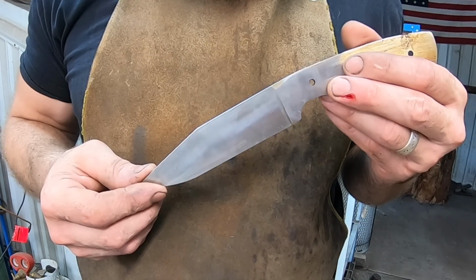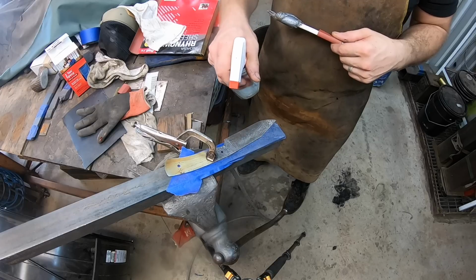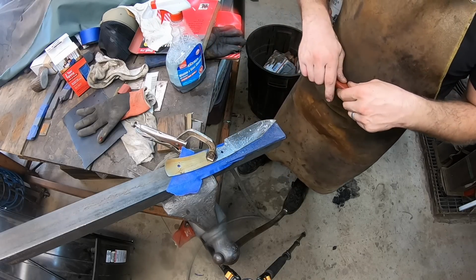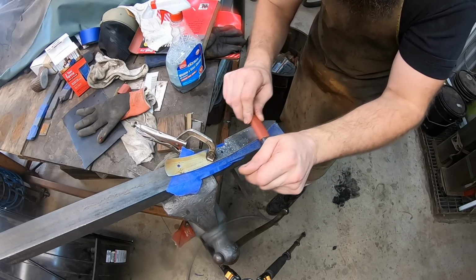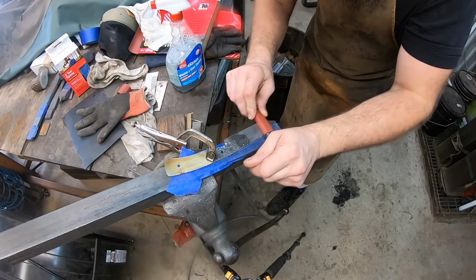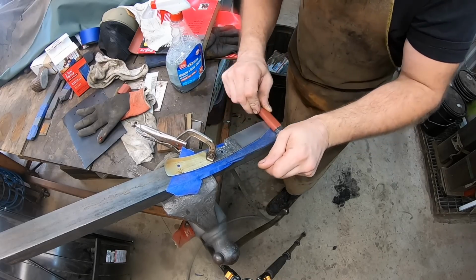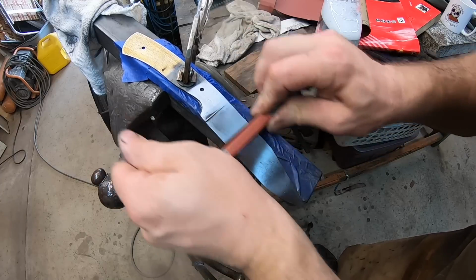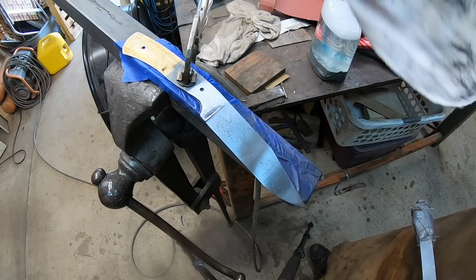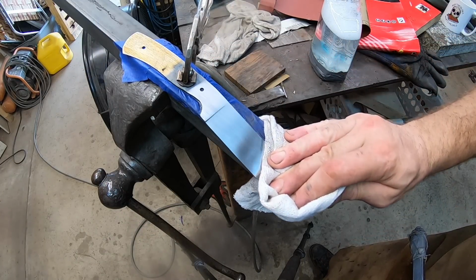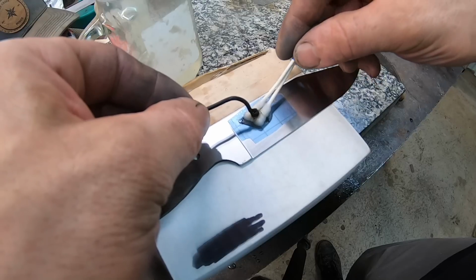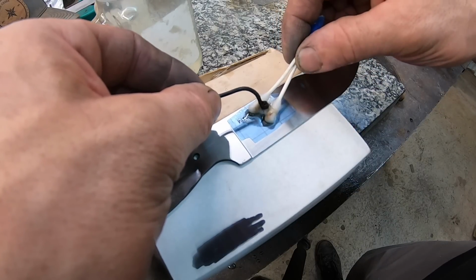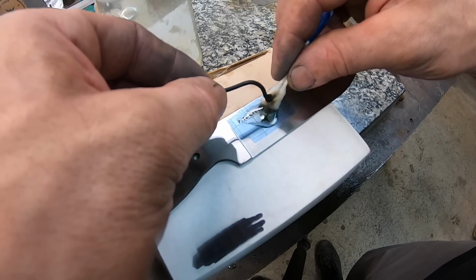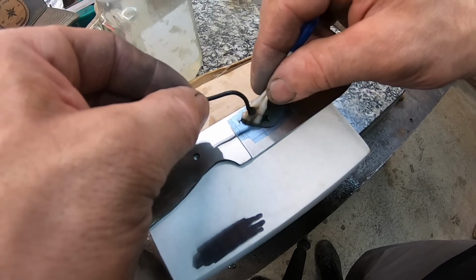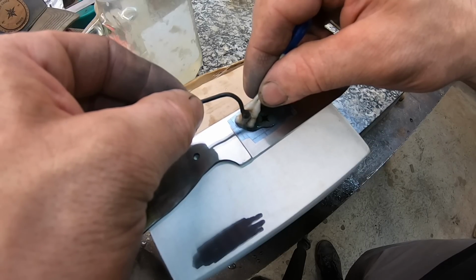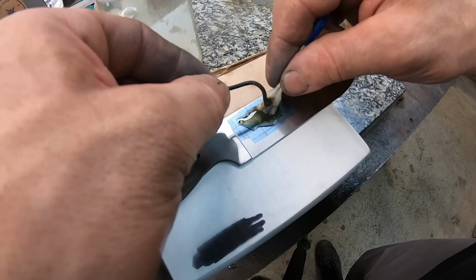You do not want any lines, which you can see right here. You can sort of see a line. That was where the O1 tool steel was starting to take a little bit of rust from the water before the pattern welded billet did, and so it was slightly discolored, and so on that one side you could see that band of steel, but other than that, there's no visible indication of a forge weld there, which is what you want.